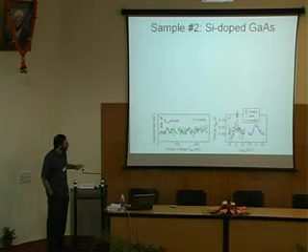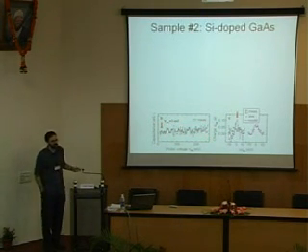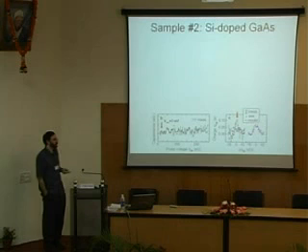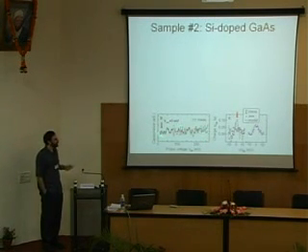If we look at these two measurements taken 8 hours apart, the dashed line versus the solid line, about 80% of the peaks are showing up in the same place. On the scale of 8 hours, something does change slowly in this sample. Most likely this folklore called DX centers, where charge is metastably trapped and then slowly leaving traps on a scale of several hours, is shifting the peaks a little bit, but more or less the data is reproducible.